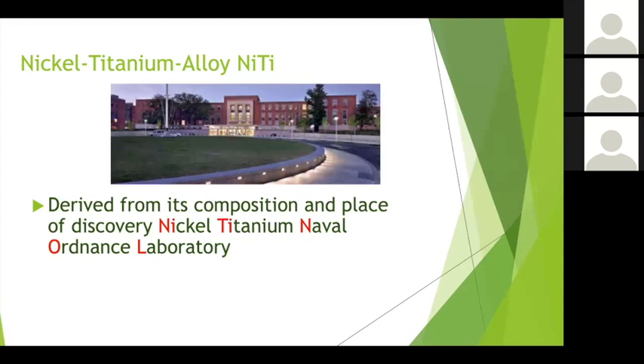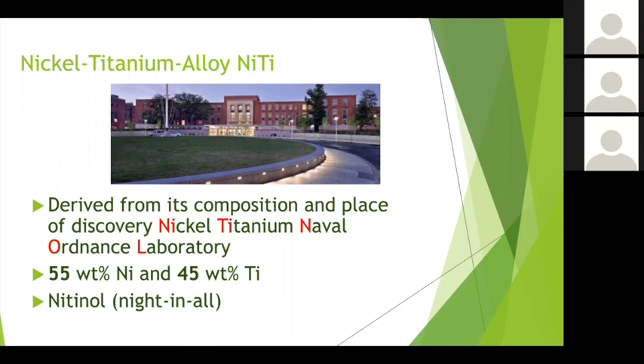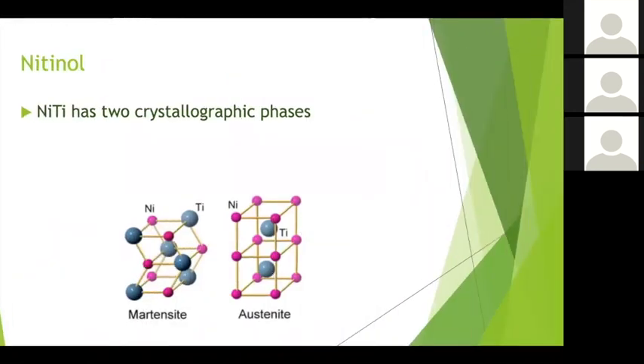And they basically put together this composition of metal that was 55% nickel by weight and 45% titanium. So we call this nickel titanium, or nitinol, based upon where it was discovered. It was Nickel Titanium Naval Ordnance Laboratory, which basically means nitinol. This is the technical term for this metal, this nickel titanium. We call it nitinol. Well, what is nitinol?